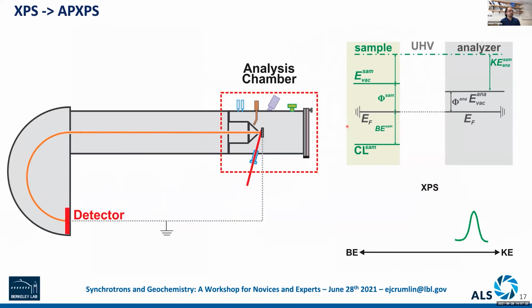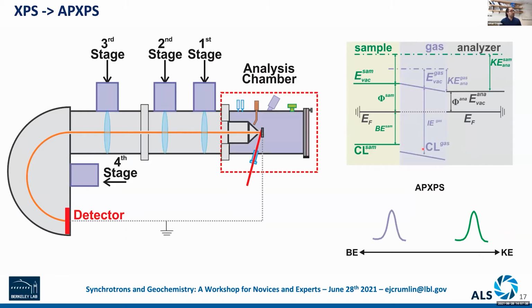And so this again is the structure of a traditional XPS system. X-ray comes in, photoelectron comes out, and that allows you to effectively get the binding energy or kinetic energy scale of the solid sample you'd be looking at. That's how this technique originated. However, with this analyzer, we can add differential pumping and some electrostatic lenses so that we can effectively have a higher pressure here where our sample is and still collect the signal. So this is where the ambient pressure comes into XPS: differential pumping and these electron optics. Now we can start to collect the gas phase and the gas-solid interface together simultaneously.